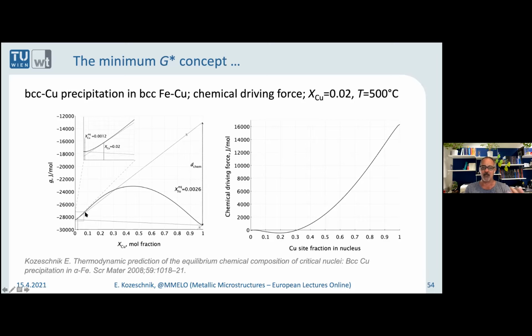So I made the calculation for the chemical driving force as a function of the copper content of the nucleus. And you will find that at 500 Celsius with 2% copper, the copper precipitate can become stable at a copper content higher than 0.3 something. That's an interesting observation, because that means that all of those compositions here have a positive driving force. So what will be the one that is observed in reality, in nature? The assumption that I made was the following. I said, why not assume that the composition will be such that the nucleation barrier is a minimum? That sounds very plausible. The one where the nucleation barrier is a minimum is the one where there should be the highest probability of a nucleus forming.